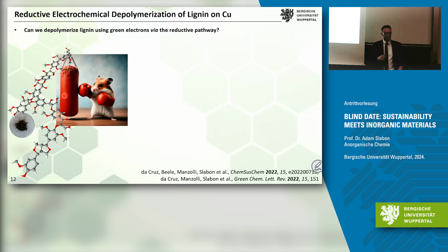But you can actually transfer your knowledge from CO2 electrocatalysis directly to lignin depolymerization. So the idea is you generate hydrogen in water, and use it to cleave the C-O bonds, for example. So we apply a copper electrode, which is a very bad catalyst for water reduction, but a very good catalyst for CO2 reduction.